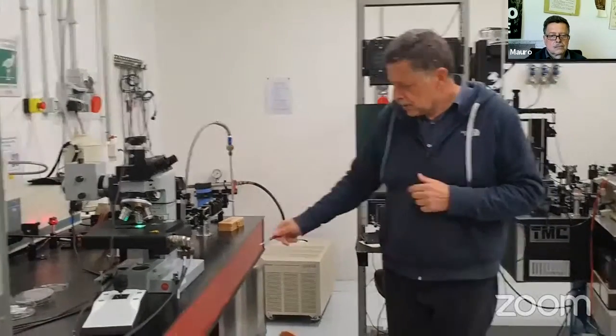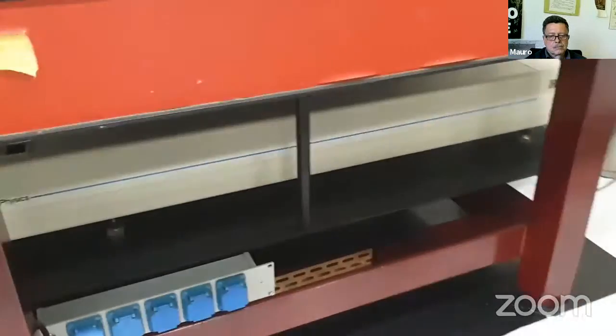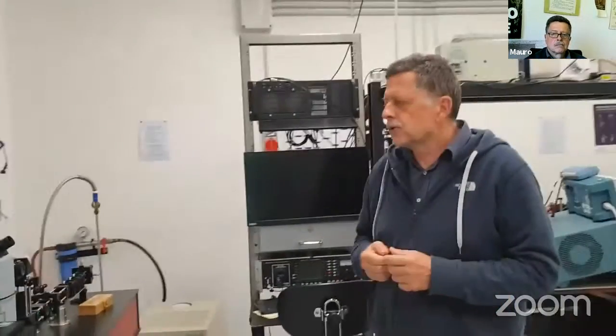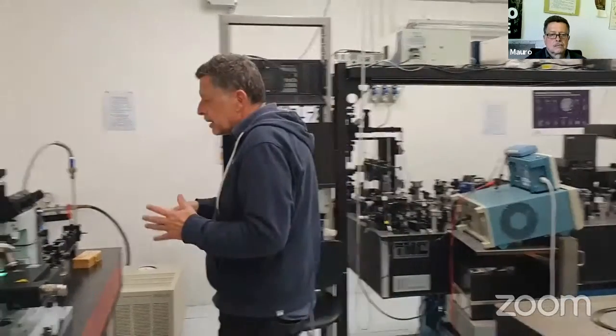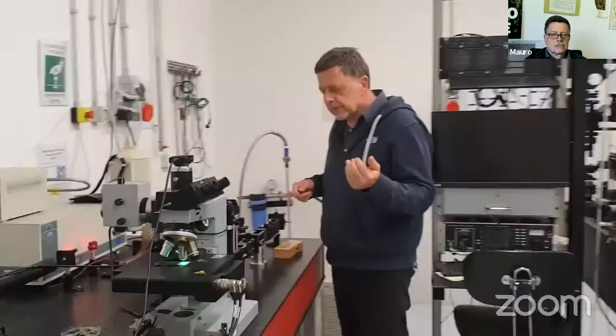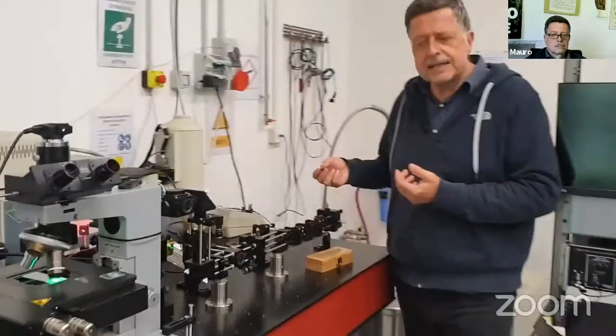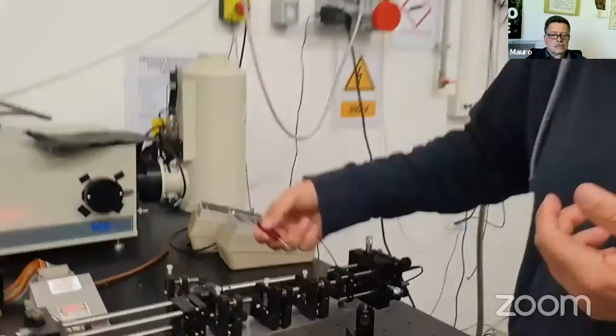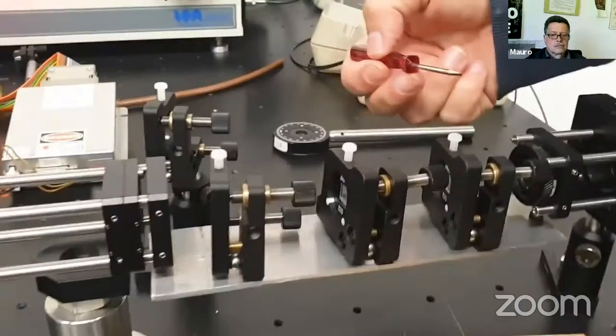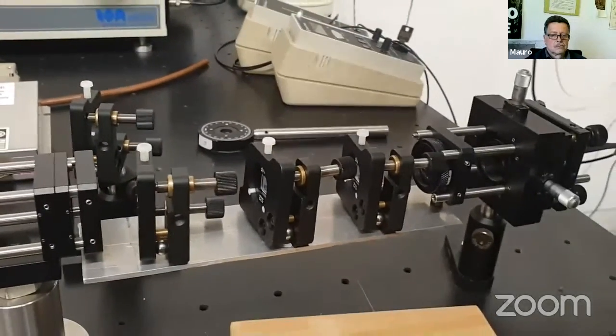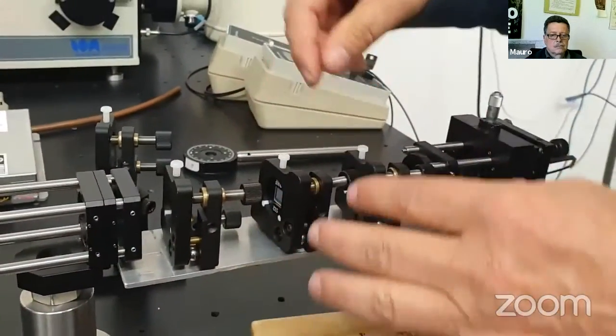Of course, here we have also, as I said before, another laser which is under the table, a very large laser which emits blue light, 478. So we actually have 3 lasers that we can change to optimize the experiment. Each time you change the laser, you need to change the filters to reject the laser, because as the laser changes frequency, the filters will also be different. So you can interchange them here.